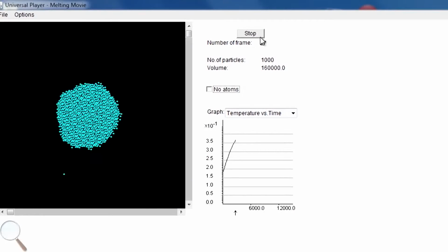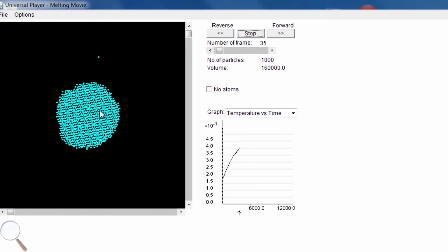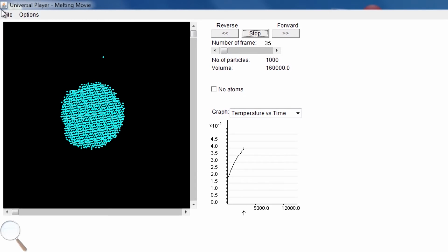We looked at that, making sure that we are able to see the transition with the temperature changing. Now we are starting with the reverse of that, going from, let us say, 1000 particles. Again, we will start with the crystalline phase and see how it melts. Here is the block we are starting with, essentially a solid block of, let us say, argon. This is a very simple calculation with, let us say, a Lennard-Jones potential function, 1000 particles, and fixed volume, E V N.